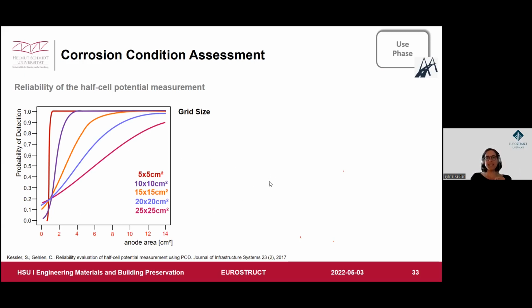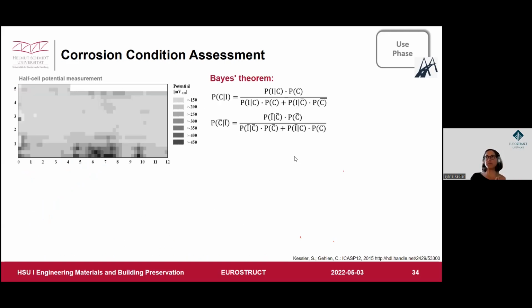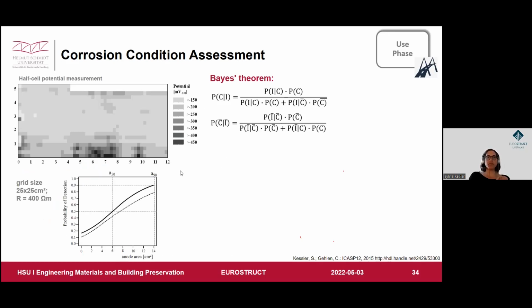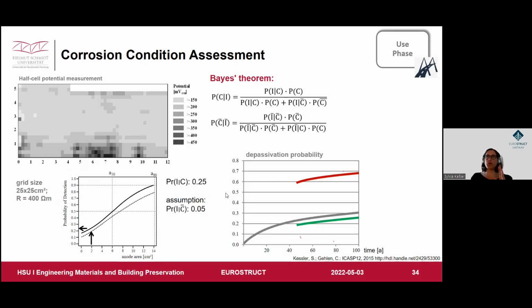And now we can take this data to apply the Bayesian theory. So we are now able to have the information about our likelihoods. This is also part of the evaluation from the slides before. Here we took a grid size of 25 by 25 square centimeters, which we did on the structure, and we assumed a concrete resistivity of 400 ohm meters, and then we are able to define the values which we need. And by applying the Bayesian theory for the first time, we can tell that as soon as we indicate corrosion by the half-cell potential measurement, our corrosion probability increases from around 22% to more than 60%. And as soon as we do not indicate corrosion from the half-cell potential measurement, the corrosion probability decreases slightly.